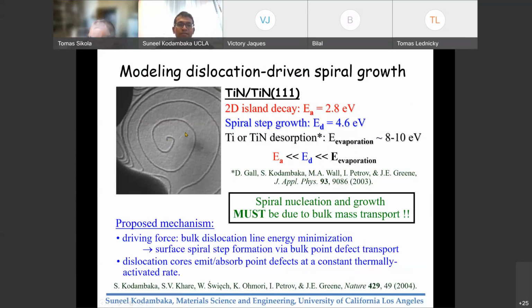And that has been observed in other material systems such as titanium dioxide and also nickel aluminide. And so we expect that because if the surface is nitrogen deficient, maybe the titanium atoms would go down and you could have pipe diffusion, and that controls the rate at which these spirals would grow. Okay, just like a fountain. You can imagine this to be a water fountain or a sink. And so you could form a mound that's growing upwards or a mound that is going inwards.